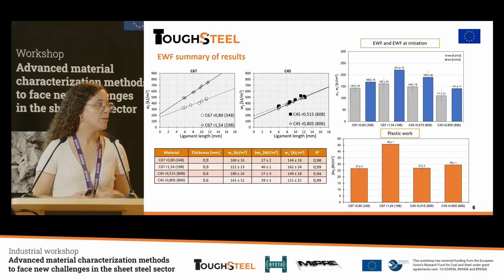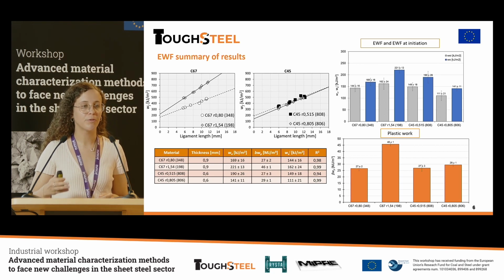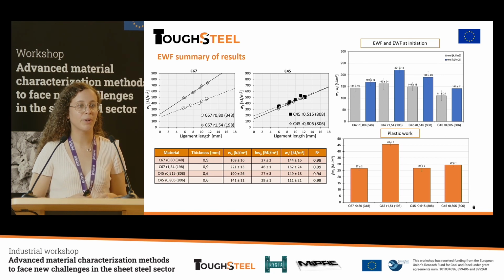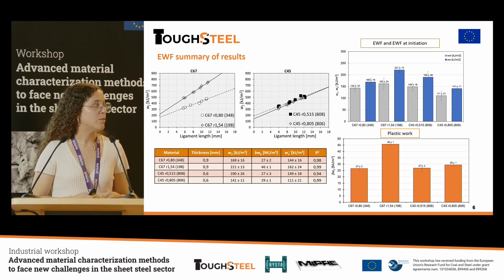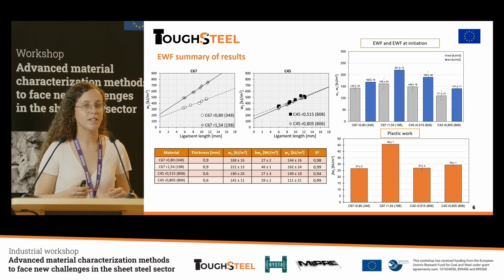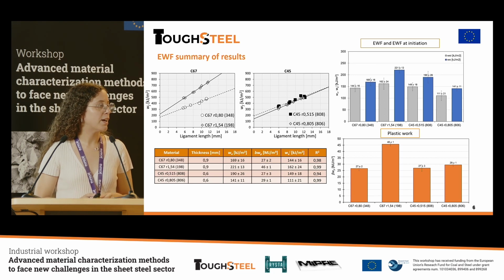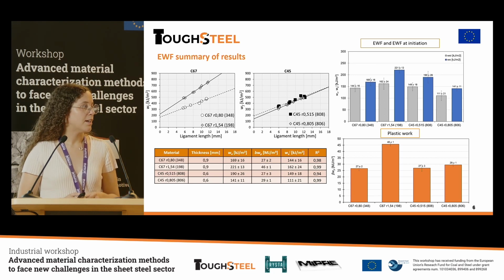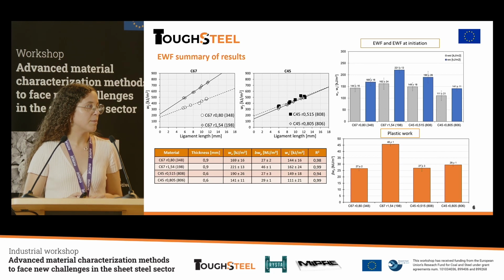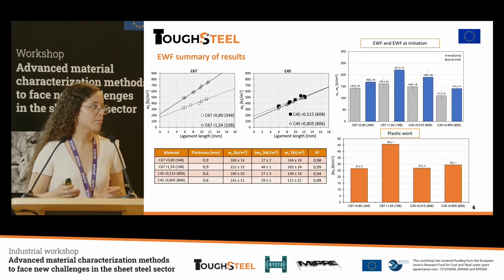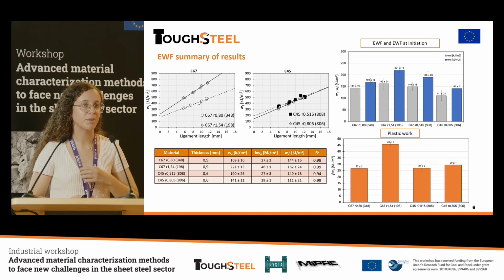We also obtained the values for essential work of fracture at initiation of propagation, which is the energy needed to start the crack propagation. And we found a similar tendency with the essential work of fracture results. In the plastic work, we could find that material C67 with higher anisotropy was quite higher than for the other materials.